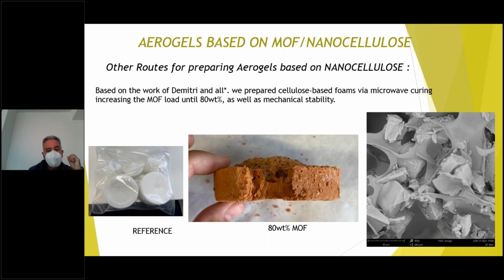In this case, we reach 80%, but we didn't try higher concentrations, because we have a very good balance between mechanical stability, ratio of MOF, and temperature resistance. In the photographs in the bottom part of the slide, we can see the different characteristics of this MOF-supported nanocellulose foam: the reference foam without any MOF, the material with 80% of MOF, and finally a micrograph where we can see the MOF crystals perfectly dispersed and distributed inside the cells of the nanocellulose foam.